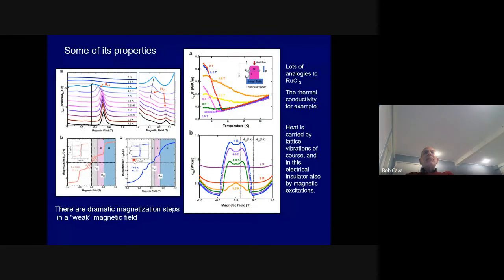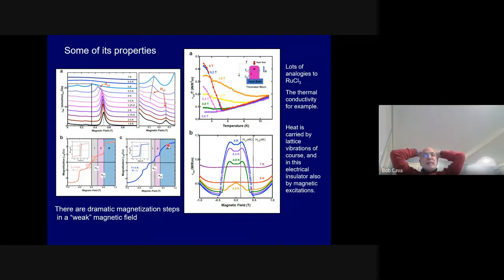Well, something crazy happens in a magnetic field. The first order look at something in a magnetic field would be to look at the M versus H loop, the magnetization of the sample versus applied magnetic field. And the thing about barium cobalt arsenate is that it has multiple steps in its M versus H curve, which indicate that there are multiple magnetic phases present. So in a field of a fraction of a Tesla, it undergoes a phase transition to something else. And by 0.4 Tesla, it's in the third magnetic phase altogether. So who knows what's going on here?